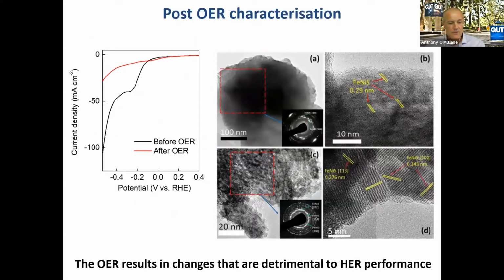One thing we did notice is that if we perform the oxygen evolution reaction and then wanted to use that same material for hydrogen evolution, there was a real drop-off in activity. Here this is the pristine material, and then if we do oxygen evolution, we can see there's a major decrease in the activity. So we're trying to understand why running it in the oxygen evolution region causes such a detrimental impact on the hydrogen evolution reaction.